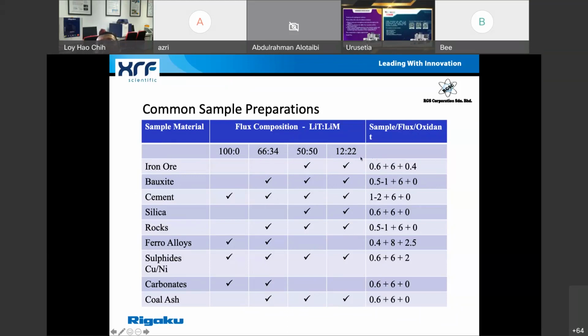And as for the weight of the samples, normally you can see that it is 1 part sample to 10 parts flux. Okay, and in this case we mix in an oxidizer because we want to ensure that all the iron ore is oxidized and becomes iron oxide before the fusion process starts. And some is without the oxidizer. So this is something that we can use if you want to go for a fusion process.